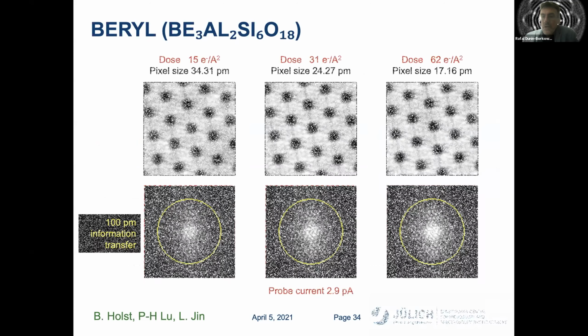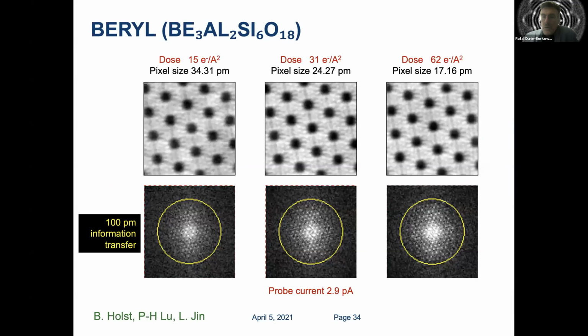Experimentally, this works very well. It's a very dose efficient technique. And on the top, I show 3 different images recorded using integrated differential phase contrast at biological electron doses of only a few tens of electrons per square angstrom.